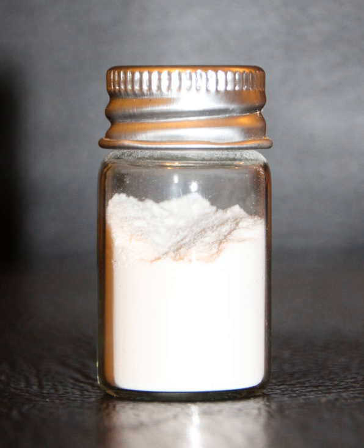The density of stishovite is 4.287 grams per cc, which compares to alpha quartz, the densest of the low pressure forms, which has a density of 2.648 grams per cc. The difference in density can be ascribed to the increase in coordination as the six shortest Si-O bond lengths in stishovite, four Si-O bond lengths of 176 pm and two others of 181 pm, are greater than the Si-O bond length 161 pm in alpha quartz. The change in the coordination increases the ionicity of the Si-O bond.